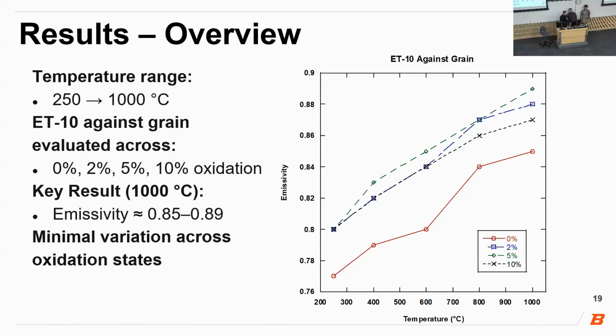What we see first is that emissivity increases consistently with temperature for every sample. Across the full range, there is some variation between samples, but there is no clear pattern tying that variation to oxidation levels. At lower temperatures, most values are relatively close with one lower outlier, and as temperature increases, the spread remains but follows the same overall trend. So from this initial view, temperature is driving the emissivity behavior, while oxidation does not show a strong or consistent effect.